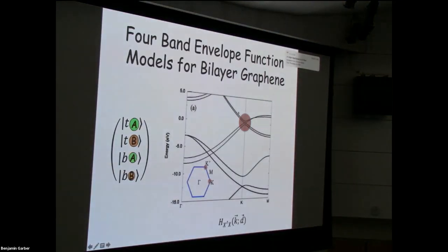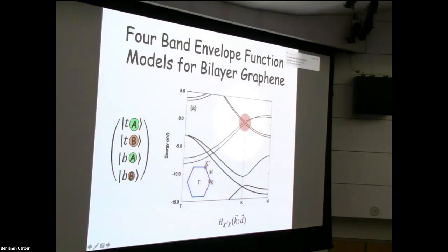So when you have a graphene bilayer, and this is very well understood and known from the properties of graphite, both three-dimensional graphite and stacking faults in graphite and so on, the main way in which honeycomb lattice carbon layers influence each other is from electrons hopping back and forth between the two layers. And this interlayer coupling produces this pattern of level repulsion of the low energy states at zero momentum in bilayer graphene.